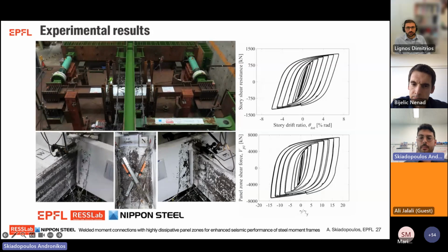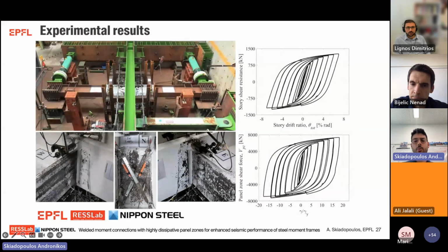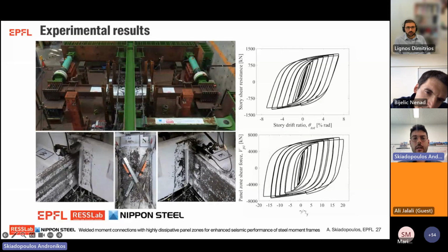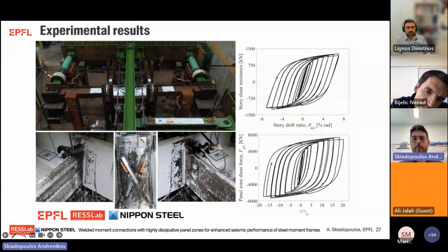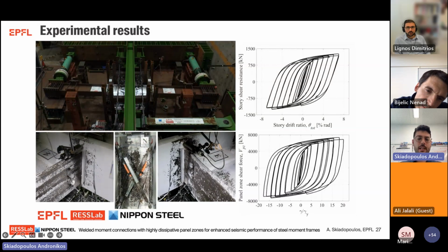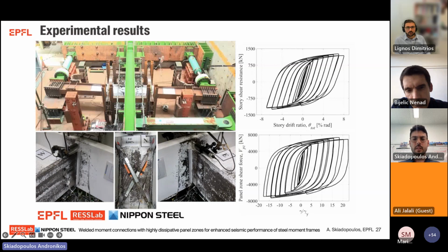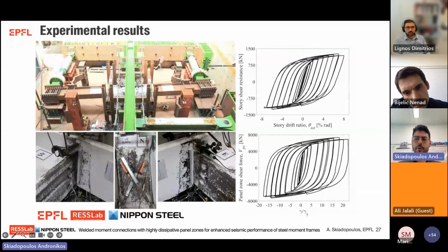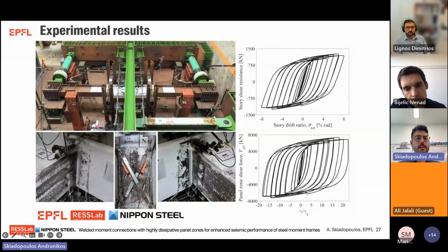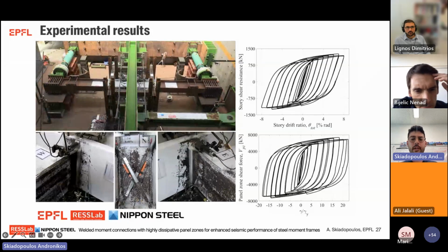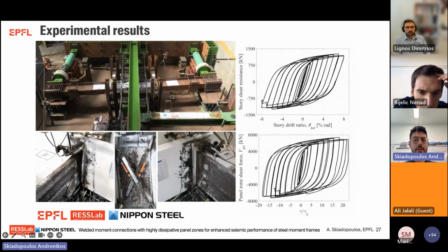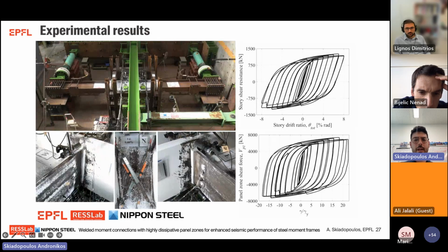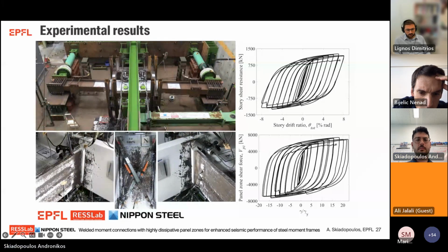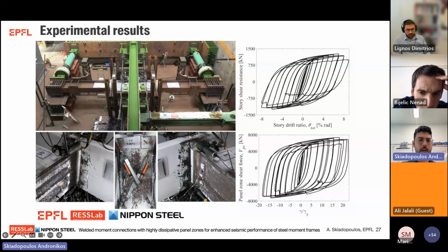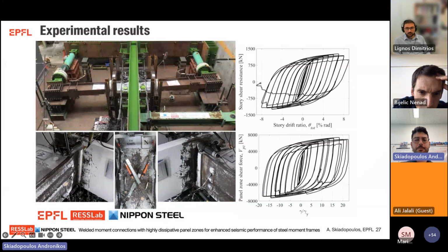Note here that after 6% story drift ratio, we continued loading the specimen because we just wanted to identify the ultimate failure mode of the beam to column connection that could be potentially important for collapse. However, the performance of the connection does not matter practically anymore, since for such lateral drift demands, the P-delta phenomena of the moment resisting frame controls the seismic response. At the end of the 9% radian amplitude, the test was terminated because of substantial loss of the load carrying capacity.